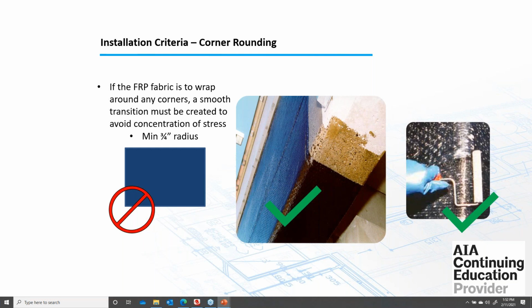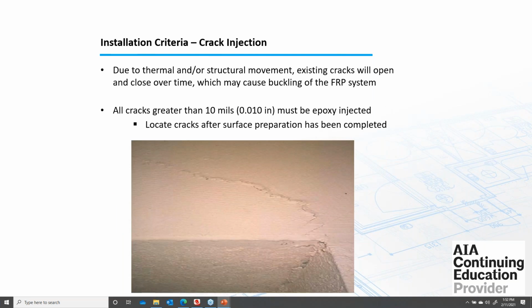The minimum radius accepted is 3/4 inch, so about 19 to 20 millimeters, but the design engineer may have to increase the radius for heavier fabrics such as the 1200 grams per square meter. Next slide. Due to thermal and or structural movement, existing cracks may open and close over time, which may cause buckling of our FRP system. So all cracks greater than 0.3 millimeters, so around 10 mils, must be epoxy injected.